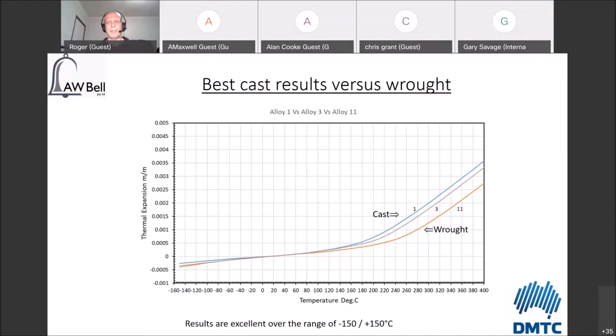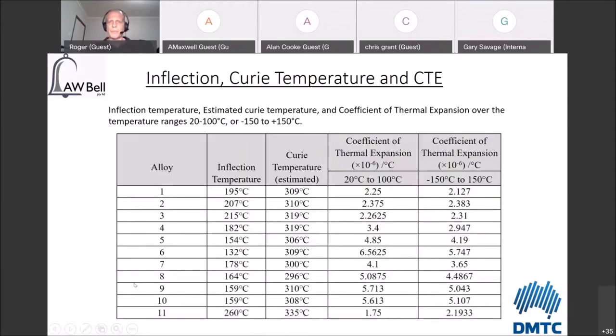And basically the reason why the Boeing material has this higher nickel content, or higher nickel specification, is because they need to operate over a different temperature range than what we're targeting. So say, for example, temperatures up to 250 degrees are very, very important for what they were looking at in terms of the carbon fiber tooling. Anyway, this is quite an encouraging result for sure.